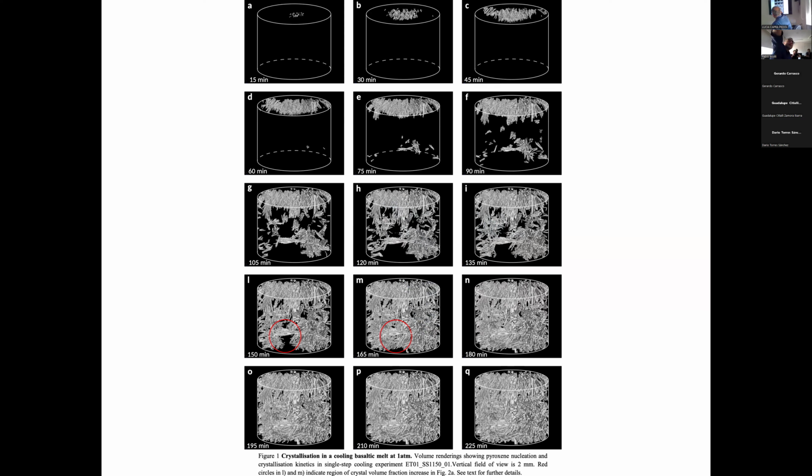We have at the beginning a heterogeneous nucleation. Since this glass is in contact with air, we have a surface in contact with air. This surface is a good surface to reduce the surface energy. So therefore, heterogeneous nucleation occurred at the surface with air, and then pyroxene crystals were able to grow in this direction, as you can see.